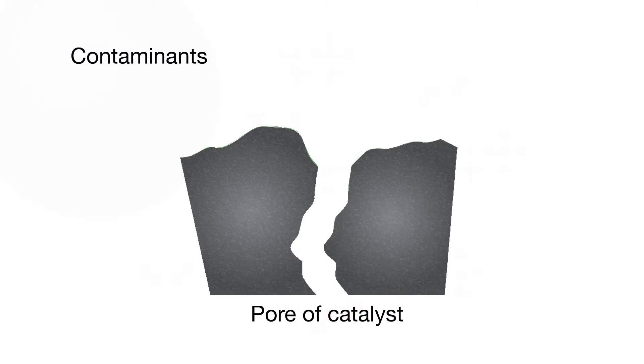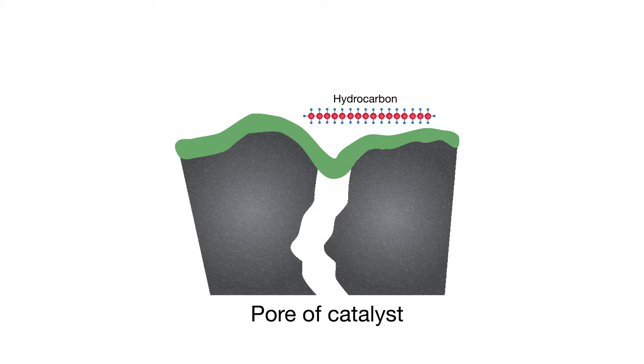During the conversion process, iron from the crude oil combines with other metal contaminants such as calcium and plugs the pores of the catalyst particles. Since this is where most of the cracking takes place, this pore blocking slows down the reactions, adversely affecting production.